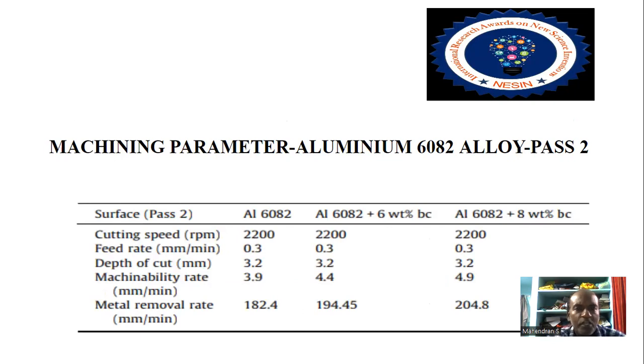This is the machining parameter with another set of experiment. Cutting speed, various parameters, another cutting speed 2200 RPM and the feed rate 0.3 and depth of cut 3.2. Machinability rate is 3.9 to 4.9. Metal removal rate also increased 182.4 to 204.8.